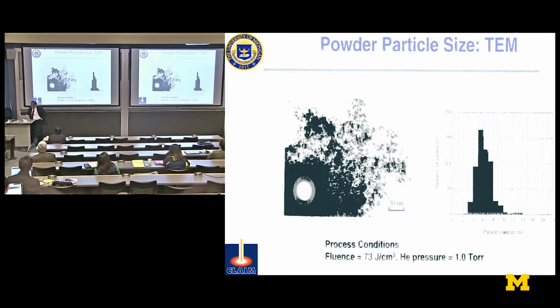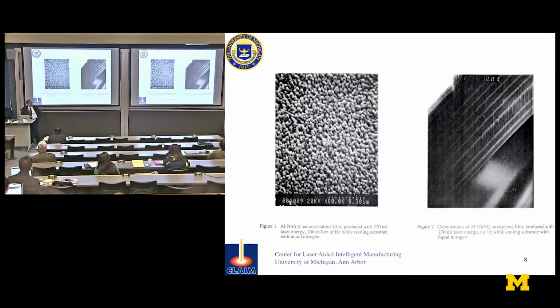So that's one of the techniques, and you can even make nanocrystalline composite. This is 5 nanometers of aluminum and 18 nanometers of niobium aluminide. Niobium aluminide has only 3 slip planes. It's brittle as hell. But if you make a composite like this, you can roll it like a cigarette paper. So the reason I gave this example is to show you the amount of flexibility you have to design the material for whatever need you have.